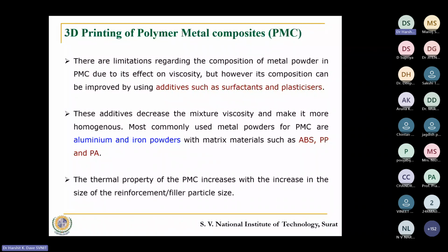The additives, surfactants or plasticizers, when they are mixed into the polymers along with these metal particles, affect the viscosity and the part becomes more homogeneous. However, the attempt which has been initiated is restricted to copper or aluminum or iron powders, and there is a wide range of mixtures that can still be investigated. So that is one such area which can be worked on rather than focusing on the printed part. Creating filaments is a very crucial and important task which we Indians can do.